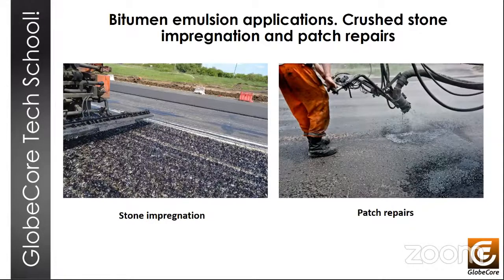When using emulsions, it becomes possible to use it on wet materials because cationic bitumen emulsions ensure fast formation of the binder film. They show high adhesion of the film to the surface of most aggregates, and overall we get good quality repair works. The emulsion consumption would be 1.3 to 1.6 liters per square meter for each centimeter of depth cut from the original surface.